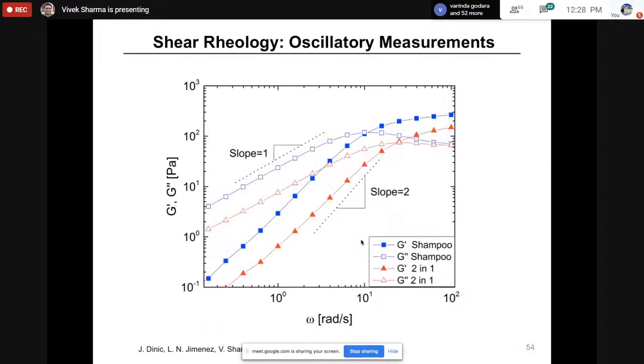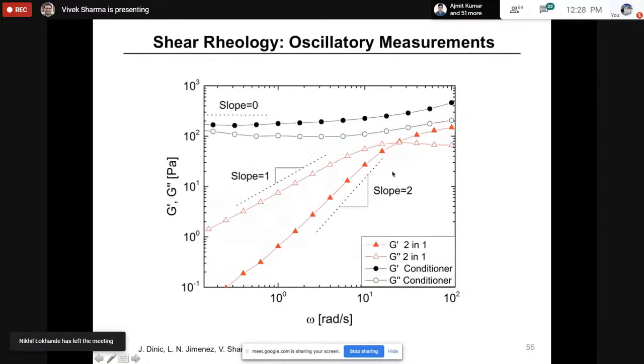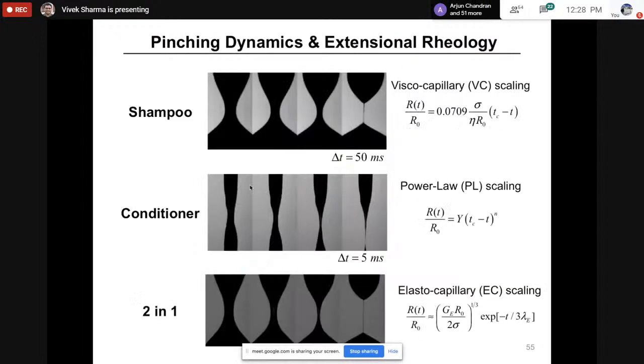A standard way of looking at elasticity is to do an oscillatory shear measurement. If you know much about these, you'll know that this is showing you quintessential viscoelastic liquid response, where G double prime has slope of 1 and G prime has slope of 2. And these are relatively nicely matched for shampoo and two-in-one. Conditioner actually behaves more or less like a gel, so it has a constant frequency independent G prime and G double prime. So there's definite difference between conditioner and two-in-one based on G prime and G double prime, but the actual shear viscosity plot didn't show you much difference.